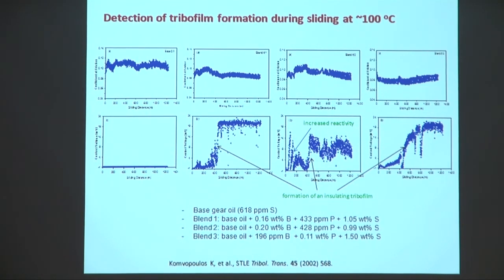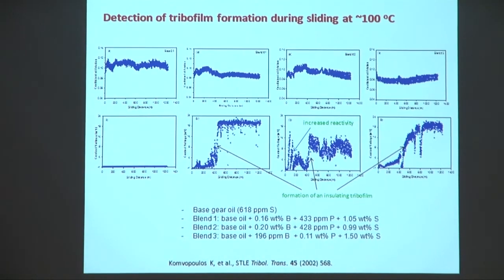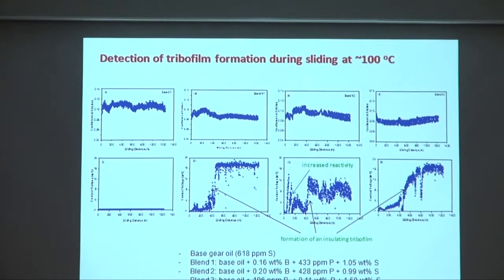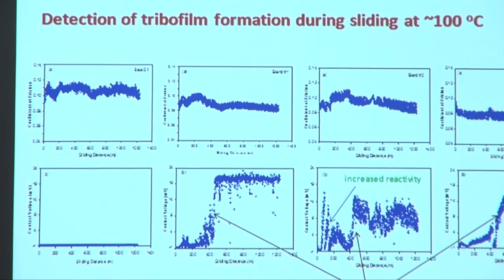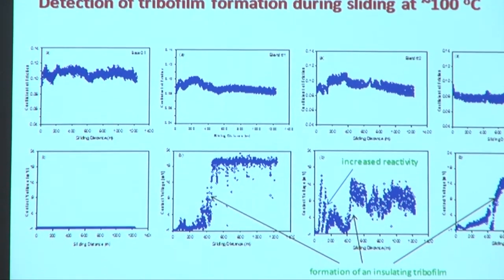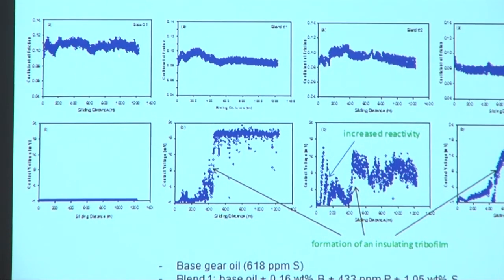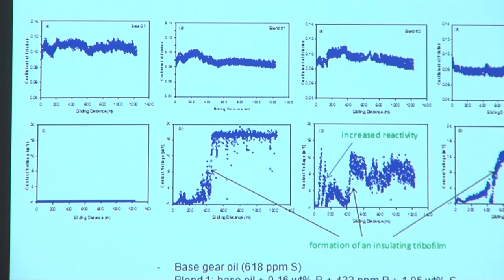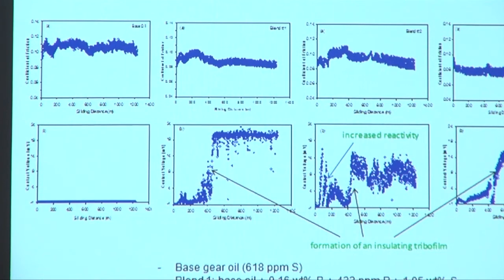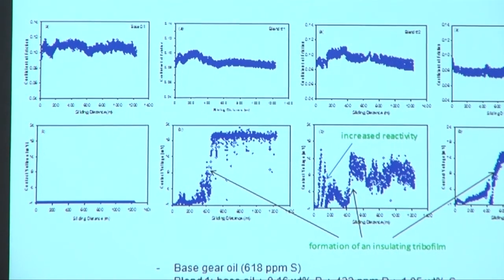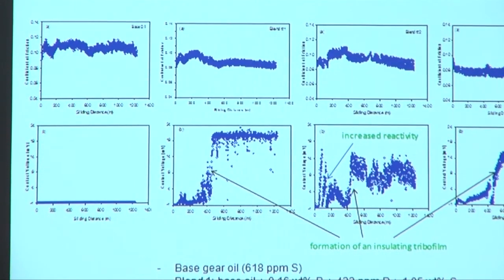So let's take a look at what happens to the same. I took out the mineral oil now, so now we have only the base oil, and then the base oil with these different formulations. Remember, the second was the one that we saw was the best performing. So if we look at the coefficient of friction and the contact voltage for the base oil that has very little sulfur, we see high friction and fluctuating friction, 0 contact voltage. You may ask about the iron oxide, whether it's an insulator and should have produced a contact voltage.